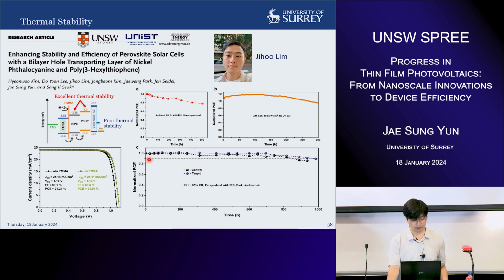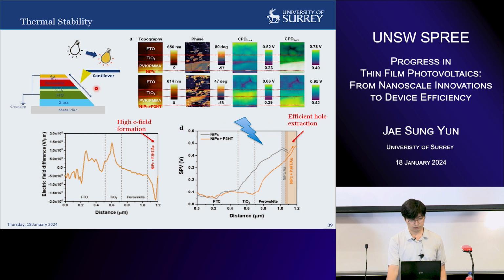So Jihu has performed cross-sectional KPFM, and we found that there is a strong electric field formed because of this hole transport layer. You can see that there is a large shift in the electric field difference, and under light illumination, such an electric field will eventually help the carriers to be extracted efficiently.